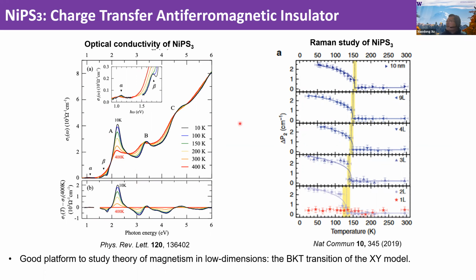There's another work that studied the Raman spectroscopy of nickel phosphotrisulfide as a function of layer thickness. In this work, they found a Raman mode exhibits a splitting when the temperature is below the Néel temperature. They measured this Raman mode splitting as a function of temperature, as shown here. They found that above the Néel temperature, the splitting vanishes. So this particular splitting can be used to measure the magnetic order. What they found is this splitting exists all the way to the bilayer, but it vanishes for the monolayer. Then what this work indicates is that at the monolayer limit, it's possible to study the BKT transition from the XY model. All this work shows there are quite interesting magnetic interactions and possible couplings between the electronic degrees of freedom, the spin, and the lattice degrees of freedom in nickel phosphotrisulfide.